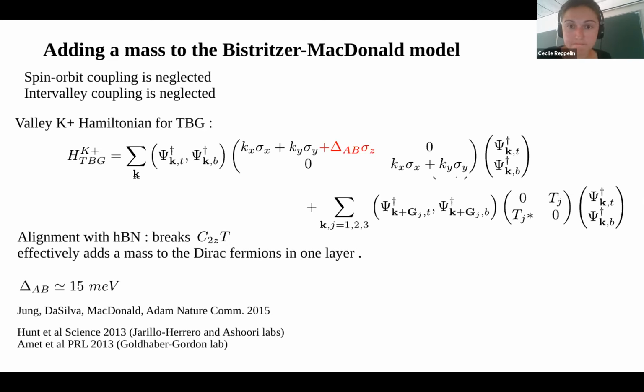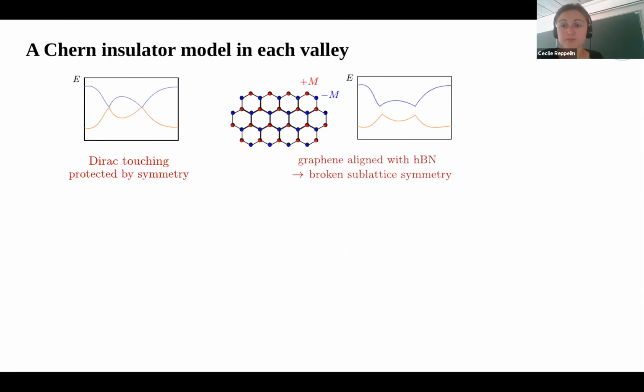All right. So you've opened this gap. You started from these conduction and valence bands that were touching each other through Dirac cones. You've added this mass term in one of the graphene layers, which has opened a gap thanks to breaking sublattice symmetry. Now this means, because you have a gap, you have a well-defined Chern number in each of the bands.